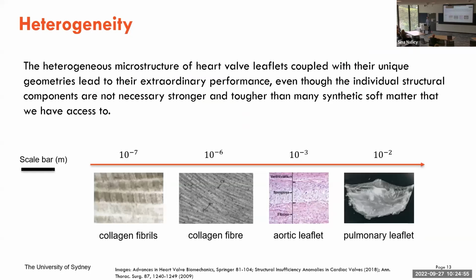At the same time, this heterogeneity that we see in the leaflets goes over a wide range of length scales. It starts at the sub-micron scale. If we look at the 10 nanometer, 100 nanometer size, you will see that these are made of collagen fibrils, which are made of oriented collagen molecules overlapping with each other. So they are already anisotropic and heterogeneous at that level.